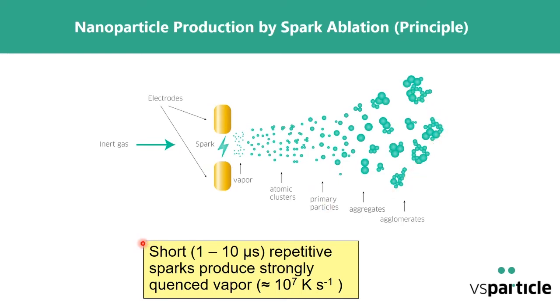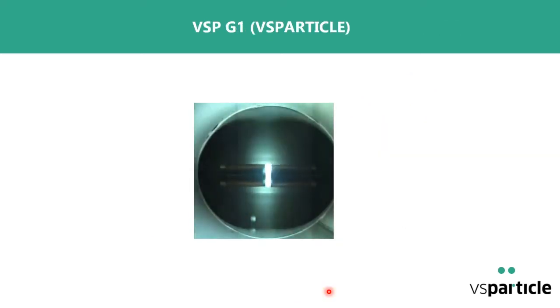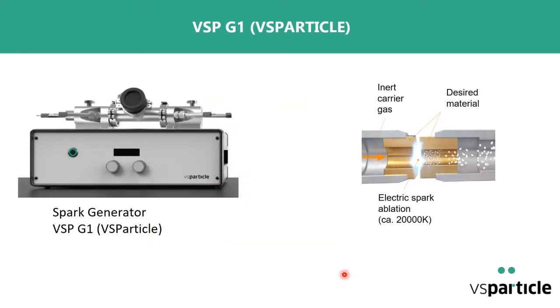Now, the trick here is to make these pulses short enough, between 1 and 10 microseconds. And that causes an extremely high quenching. That means that the very high temperature of the spark, which can be 10 to 20,000 degrees C, is cooled down to room temperature practically immediately with this very high gradient marked here. And this is what the spark generator of VSParticle sounds like, and this is what it looks like.